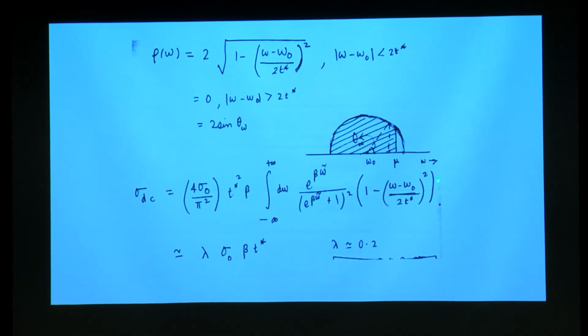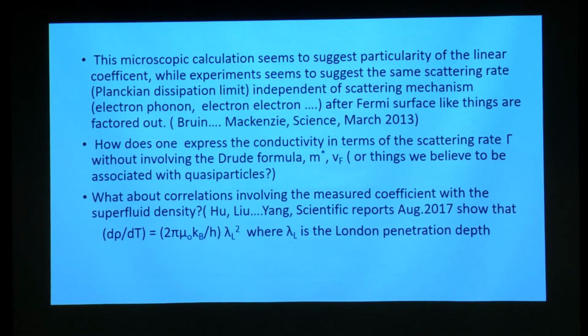This spectral density is non-zero only when this frequency difference is less than 2T star, and is 0 above it. So the integration actually extends only to a length of the order of T star. So you find that the DC conductivity is inversely proportional to temperature and is proportional to T star. Okay, so this is one other calculation which gives you a similar conductivity and therefore a similar linear resistivity.